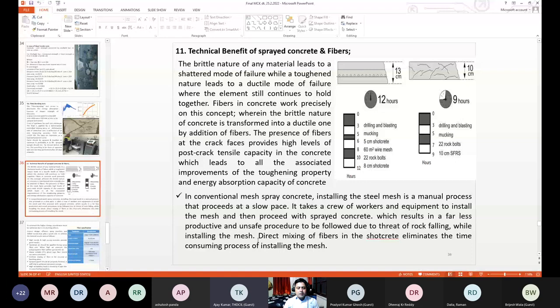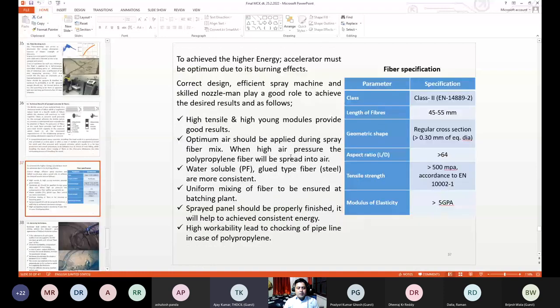Now you know that to achieve higher energy, the accelerator must be optimum due to its burning effect. Fiber specification: which fiber is generally being used? Class 2, 45 to 55 length, cross sectional shape 0.3, and the aspect ratio should be more than 64, and the tensile strength of the fiber should be 500 or more, and the modulus of elasticity should be more than 5 GPa. Its benefit: high tensile strength and high Young's modulus provide good results.